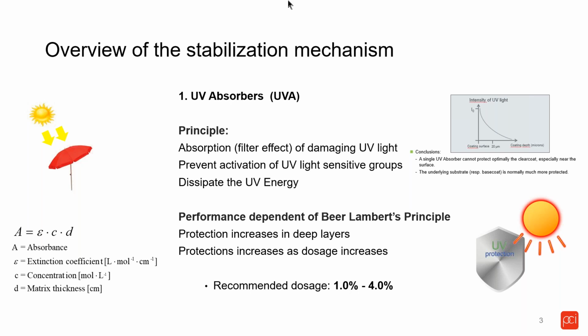Very important about the UV absorber is the Beer-Lambert principle, which pretty much dictates that the absorbance, which is how much light is filtered by the UV absorber, is directly proportional to the thickness of the coatings, to the dosage of the UV absorber, and epsilon, which is the extinction coefficient. The extinction coefficient is actually based on the molecules, which we will talk about on the next couple of slides. But again, more importantly, to know about UV filters is that their performance is directly proportional to the dosage and the thickness of the coatings, which basically means that if you have a coating of, for instance, 2 mils, and if you are using 2% as an example of a UV absorber,